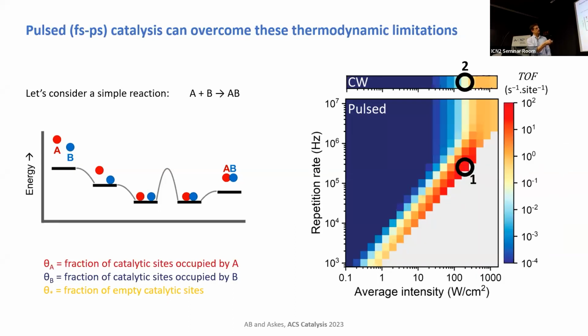So this would be continuous wave or steady state. And the turnover frequency is very low at very low intensity, and then it goes to a maximum over here, and then it goes down again. So this is the turnover frequency as a function of intensity. But now, if we have a laser pulse, we can also vary the repetition rate, kind of the sound of our laser pulse, the music that we're playing. And if you vary the repetition rate, there are certain regions of intensity and repetition rate where the turnover frequency is orders of magnitude larger for the same intensity.